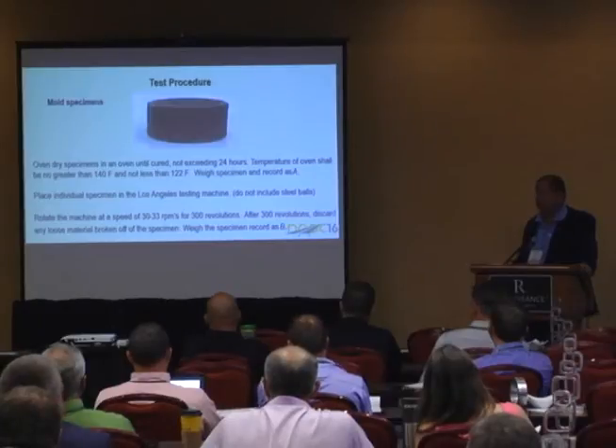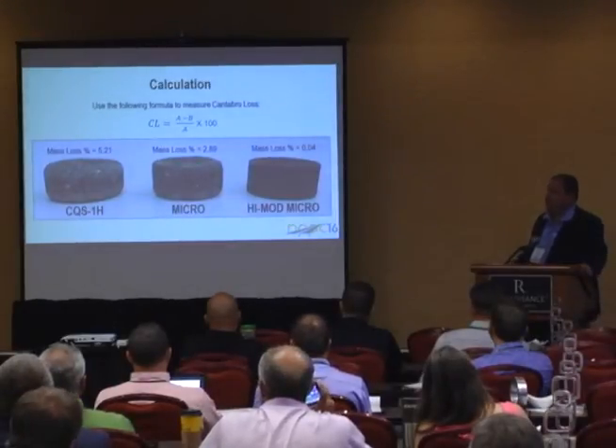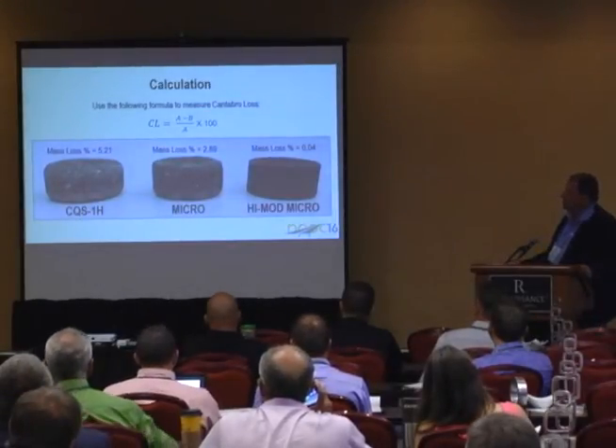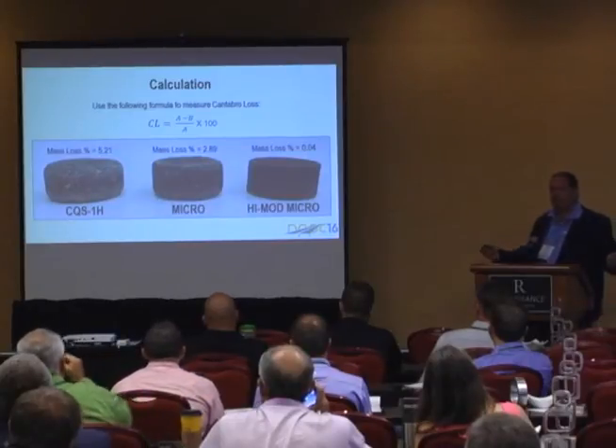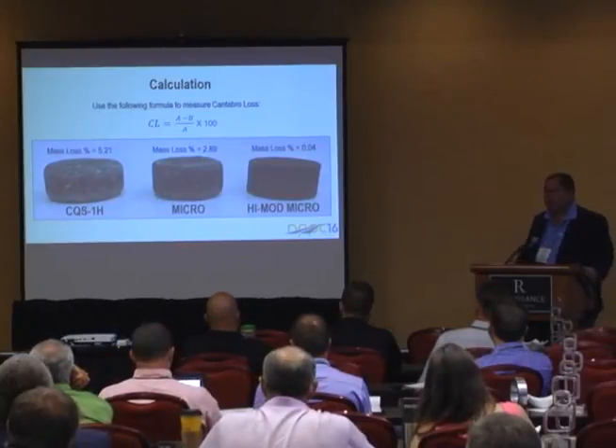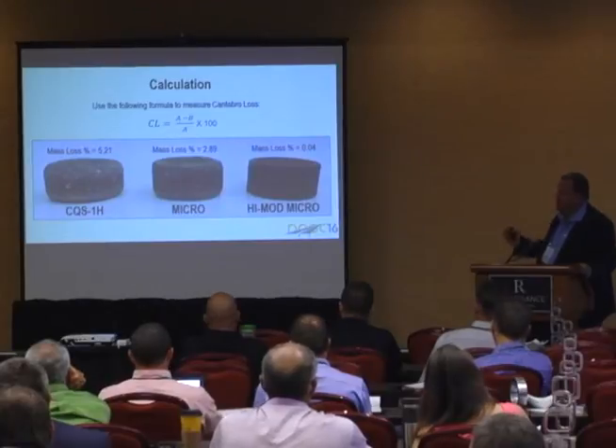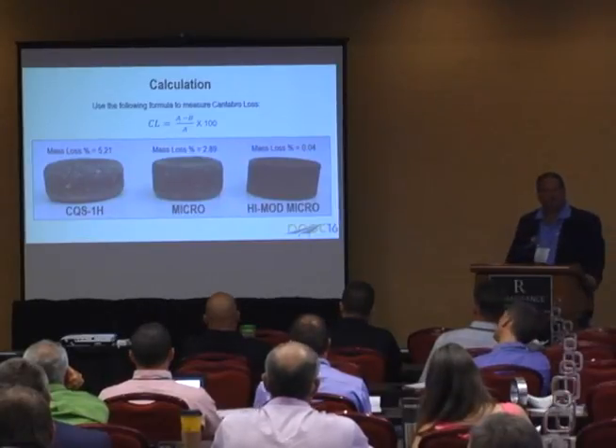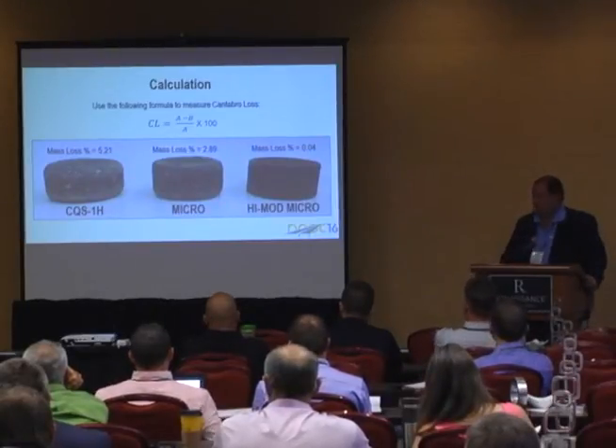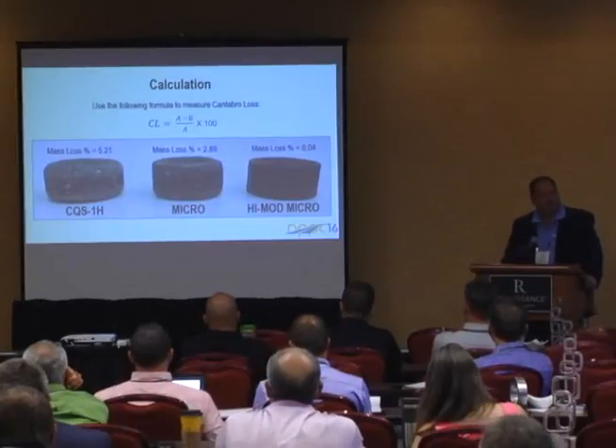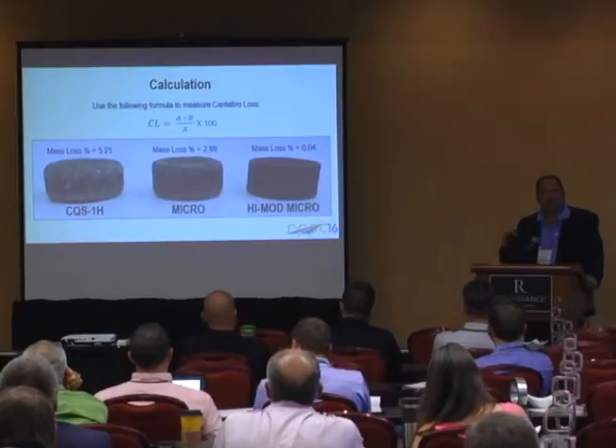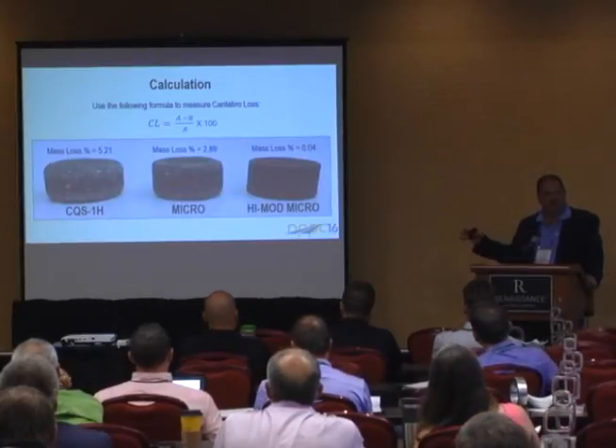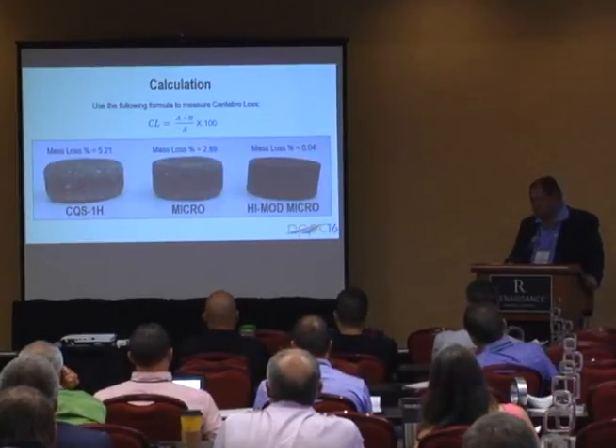So what does it look like at 300 revolutions? Well, here you are with the durability. This is a traditional CQS, slurry seal, non-modified. Then you have your traditional micro, could be 3.5 to 4% modification. And then you have the high mod, which is probably up to 5.5 to 6, but we're not worried about the percentage of polymer because we have a good test procedure to identify this durability.